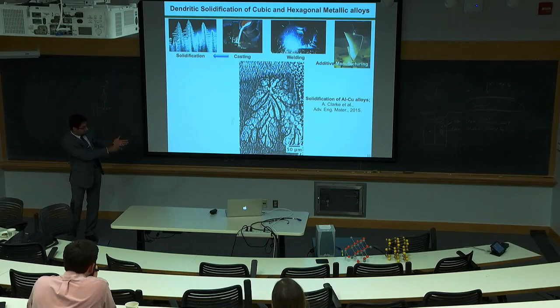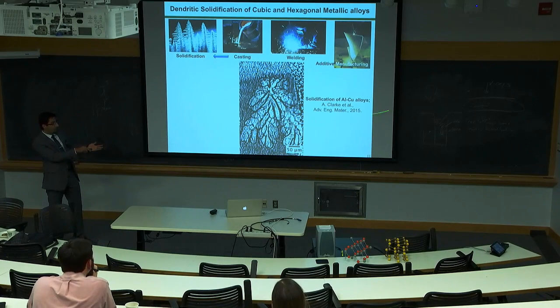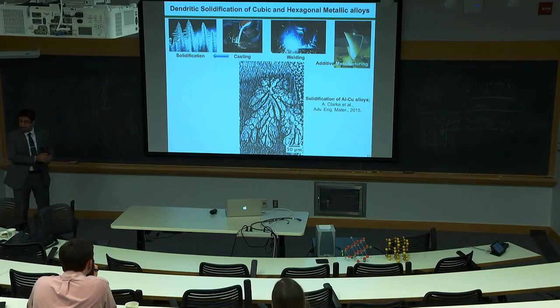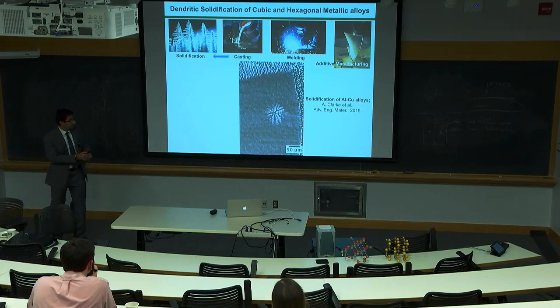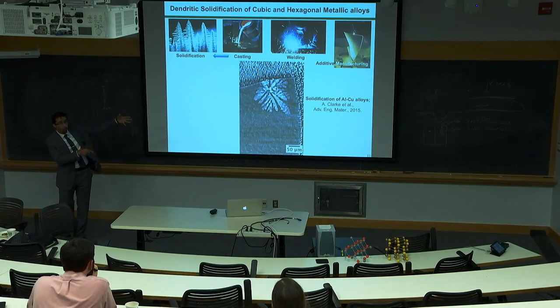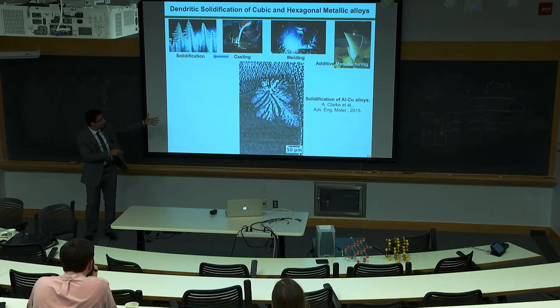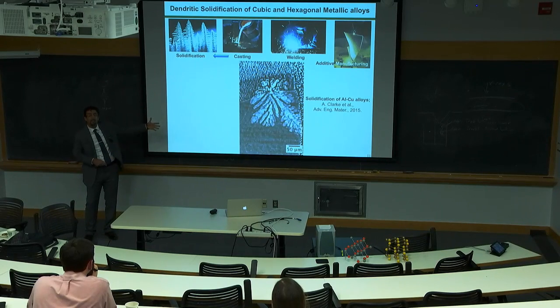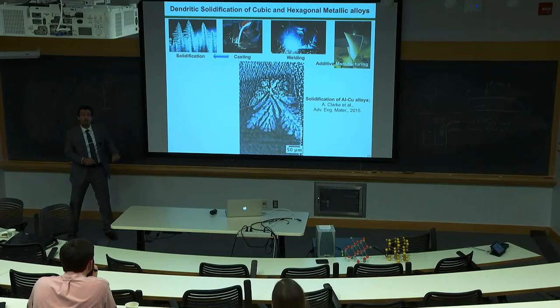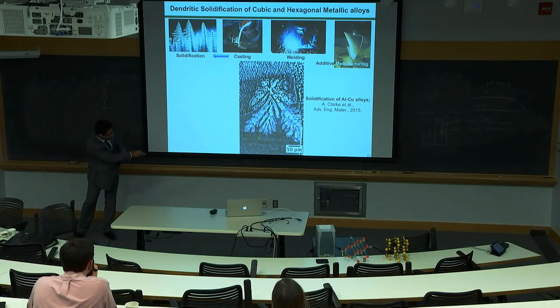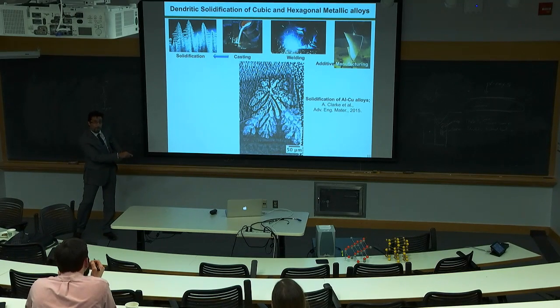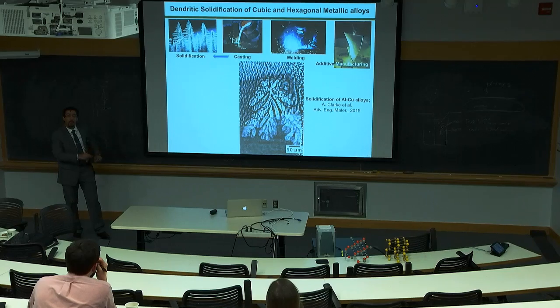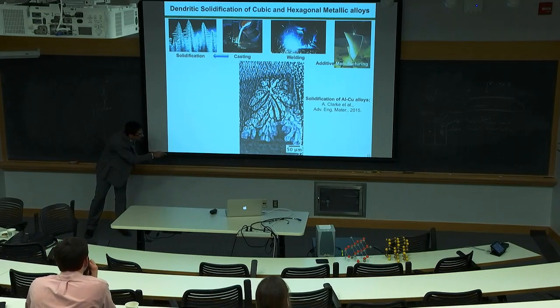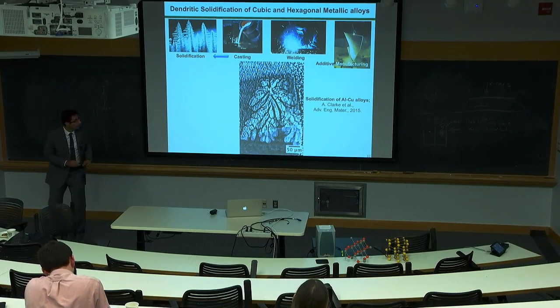So this is one example from one of my colleagues in Los Alamos National Lab, Amy Clark. They have been working on in situ experiments looking at how the dendrites form and evolve in this lightweight aluminum copper. As you can see, these dendrites, so we call it dendritic solidification. These dendrites actually determine the mechanical properties, the spacing between the dendrites, okay?